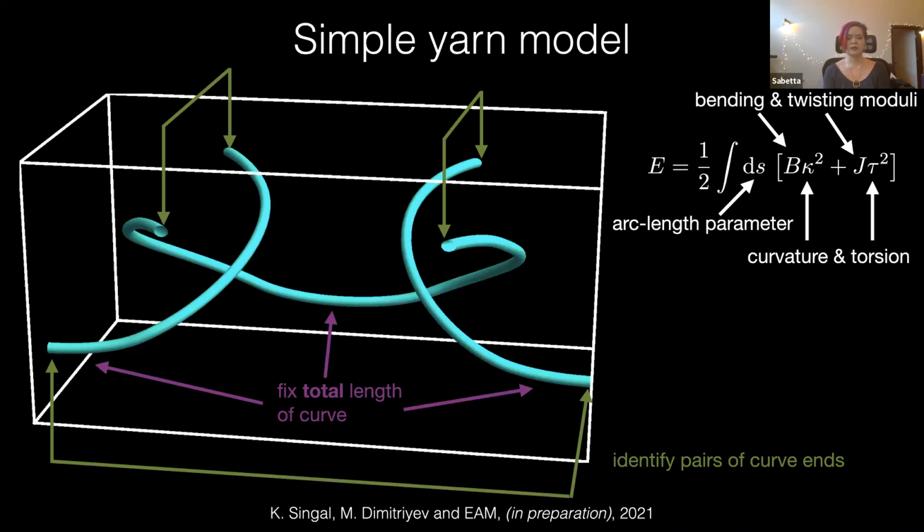Basically, we only consider curvature energy. We can consider torsion, but in spun yarn, the bending modulus is a lot greater than the torsional rigidity, so we can basically ignore that component. This gets to be more complicated if you deal with monofilament, which it seems like a lot of physicists do, but for the resulting textiles, you really need to have more terms in your elasticity to be able to completely model them compared with spun textiles.